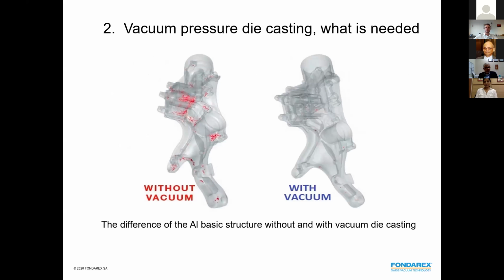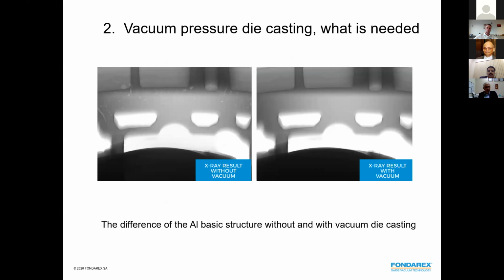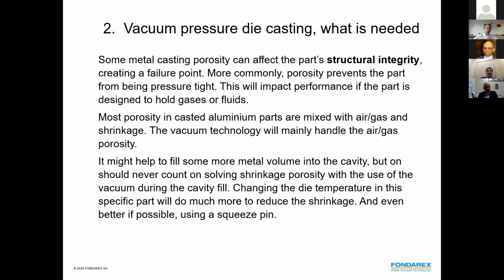If we make a tomograph of a pressure die cast part without vacuum, we will find some microporosity in many different places. And even if we cast with vacuum, there will still be some small remainders in some places. So this may be a mix between shrinkage, air and gas. In an X-ray, we can see some shrinkage, even a little with vacuum here, but it gets significantly better. So structural integrity is a big failure point in basically all pressure die casting parts.